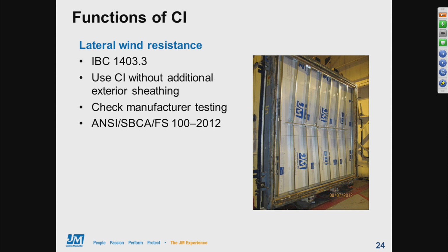Wind resistance testing can also demonstrate how foam sheathings can be used without an additional exterior sheathing. And by additional exterior sheathing, here we mean things like exterior gypsum board or OSB. So as with air barrier performance, always look for system level testing from your manufacturer. The photo that we have here in the slide shows an example of only 1 inch thick AP foil-faced foam sheathing mounted to a 20 gauge steel framed wall. So this was actually our air leakage test system, and this system was tested for air leakage across a range of increasing air pressures. And at the very end of the test, we ended up with an air pressure that was equivalent to a 200-mile-an-hour wind. So as you can see in the photo, there's a little kink in those steel studs. The wall itself buckled, at which point we stopped the test for safety reasons. But it's important to note that the foam boards never broke and the tape seams never failed, even at this really high air pressure.